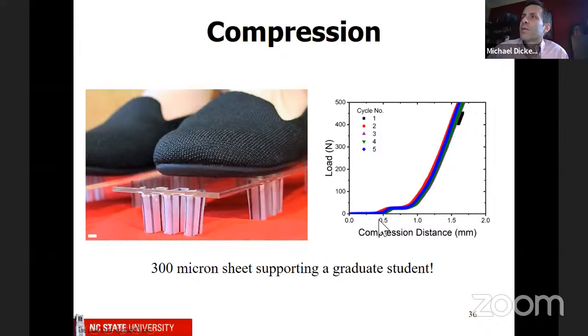And you can see that when we compress this, this is the compressive strain, the load shoots up, and we actually reach about 500 newtons. At that point, we have to stop because otherwise it could break our instrument. And so these things are very, very stiff.